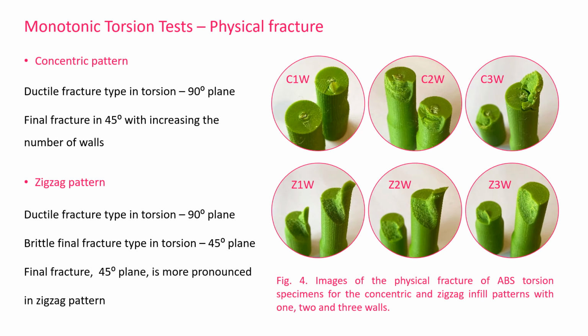From Figure 4, it can be observed that the concentric pattern tends to fracture in a 90-degree plane with the specimen longitudinal axis, characterized by a ductile fracture type in torsion, and with increasing the number of contours, close to the final instant, the specimen's fracture is in a 45-degree plane, showing a more brittle fracture type in torsion.